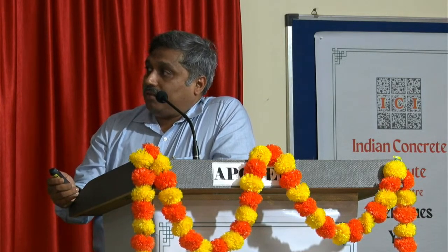I'll run a bit fast on these slides. The most interesting thing would be to watch the 365 days. 40% replacement giving up to 95. Look at the pure OPC, it is stuck at about 67, and even a 70% GGBS is going till 77. So any concrete where you don't require a very high early strength, especially a raft foundation or something, you can go with high replacements. For applications where you require higher early strength, we can design to choose around 35, 40, 45%.